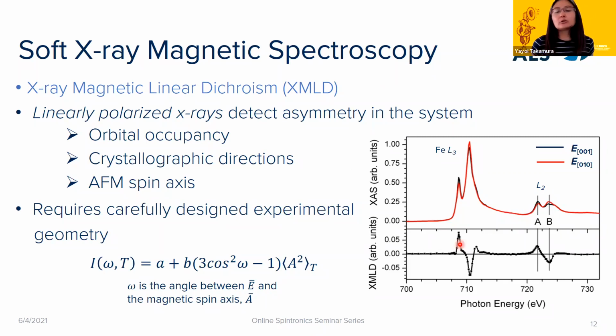So if you're able to either have reference data or do some simulations, you can then have a fingerprint of the source of your dichroism spectra. If it is from an antiferromagnetic source, then this is the intensity function. In this case, instead of a cosine dependence, it's a cosine squared dependence, right? So a different functional form, and so it separates it from the circular dichroism.